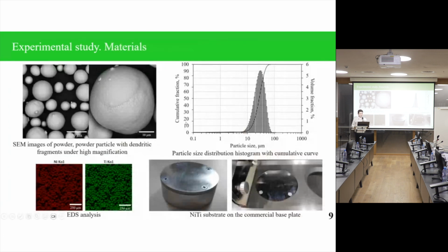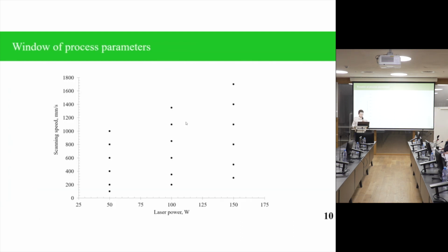In the experiments, a spherical prealloyed nitinol powder was used. Prealloyed means that each particle inside the powder is an alloy itself. The powder is not a mixture of nickel and titanium powders. It's important to receive homogeneity in our samples and to provide reasonable metallurgical bonding between the substrate and samples. And an in-house built nitinol substrate was manufactured. For the study, a relatively broad window of process parameters was utilized. It is shown here in scanning speed and laser power coordinates.